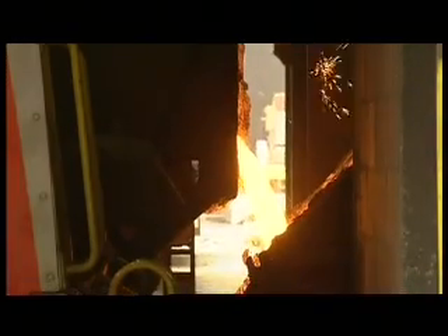The hot metal from the blast furnaces is now ready to be converted into liquid steel. Each torpedo ladle can carry about 170 tons of liquid hot metal to the steel plant. If necessary, the hot metal is first desulfurized. Subsequently, the torpedo ladle is emptied into the hot metal ladle. A crane takes this ladle to the slag removal station, where the slag originating from the blast furnace and desulfurizing process is removed. After the slag removal, the hot metal is charged into the tilted BOF vessel.